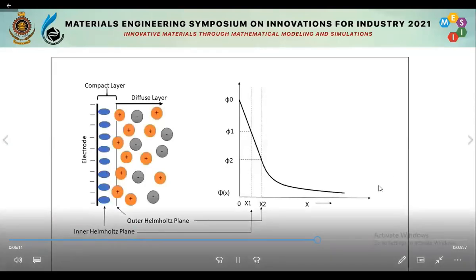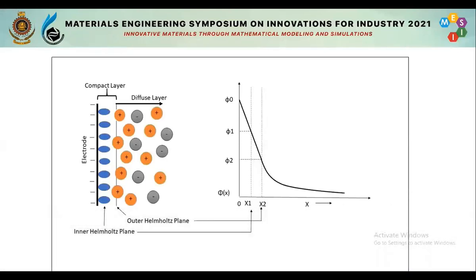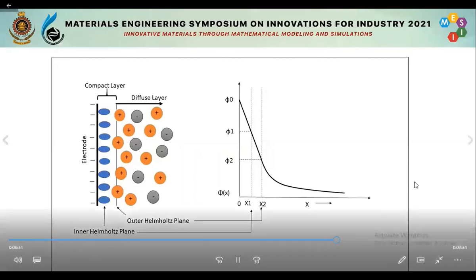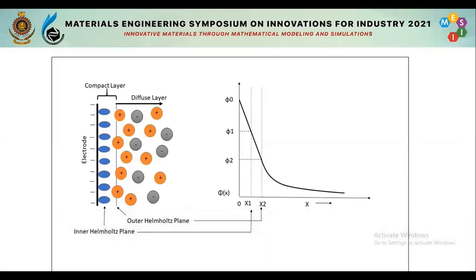We consider the 1:1 symmetric electrolyte, aqueous electrolyte with a very low concentration, in our work. The concentration of the electrolyte used for calculations is 0.001 moles per cubic decimeter, and the applied voltage range was below 5 millivolts. These values are used because we developed the theory of effect of electrode roughness on the double layer capacitance based on Stern model, which is valid in lower electrolyte concentrations and applied potential.